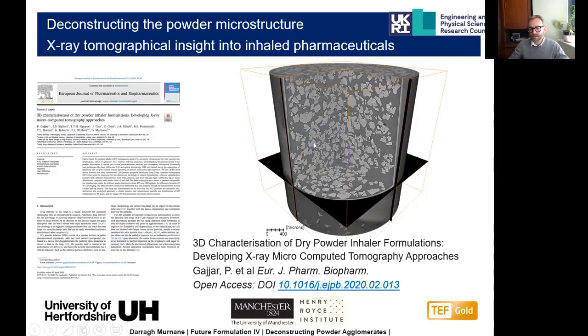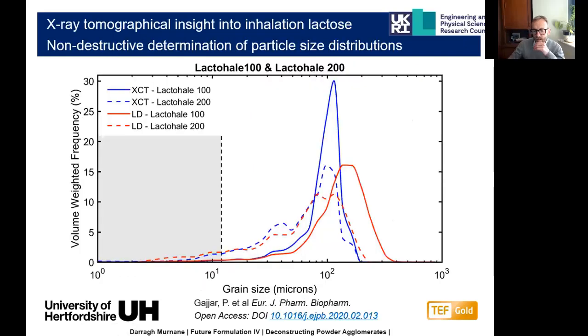So this is really the first time that we've been able to look at materials on the scale of inhalation formulations using three-dimensional imaging techniques, which is really quite exciting for us. We can start to pull out, as Parmesh said, statistics of particle size distribution, but we can also now start to separate the impact of preferred orientation.